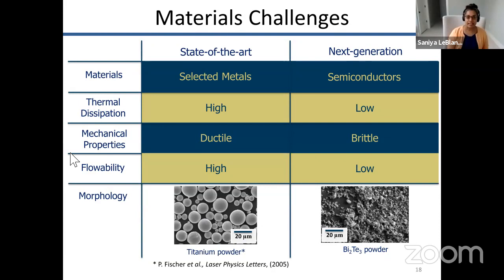And when we looked at the work going on in laser powder bed fusion, folks who might be familiar with it are familiar with it being used for metals. So typically, in metals, the column on the left shows you the characteristics for metal materials. The thermal dissipation is higher because the thermal conductivity of the material is higher. The material itself is ductile, and you can get the starting powder material in the form factor that you see in the scanning electron micrograph at the bottom, where the particles are round, they're spherical, and so you have a decent amount of flowability, the ability of moving that powder.